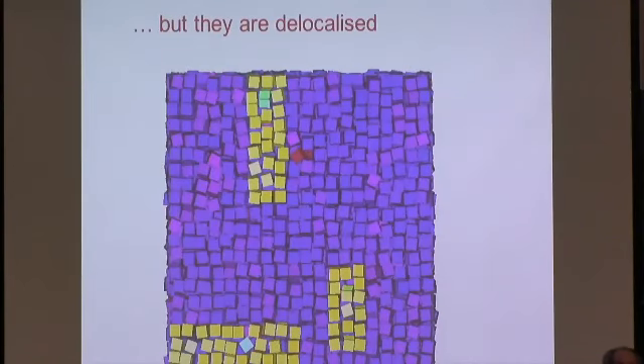Cubes don't interdigitate like spheres, so they can slide. And so if you have one vacancy, it's a bit like this game where you have to move letters into place. You basically have one vacancy in a line, and you gain free energy, or you gain entropy, by having the whole thing delocalized over the entire line. And so what you see is a delocalized strip of particles that together could concentrate somewhere to form a vacancy, but they don't.